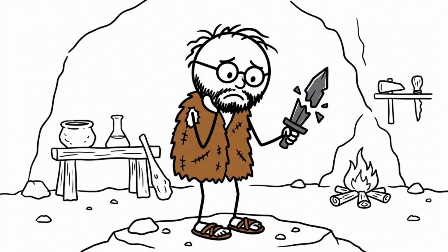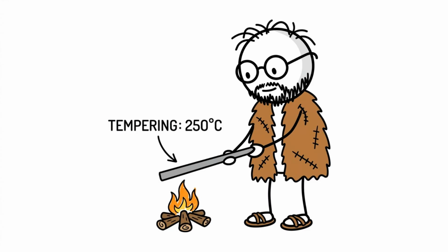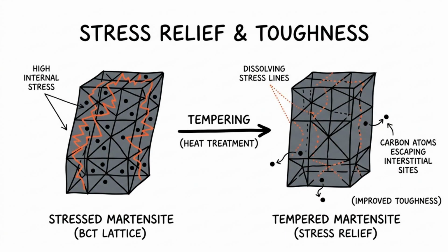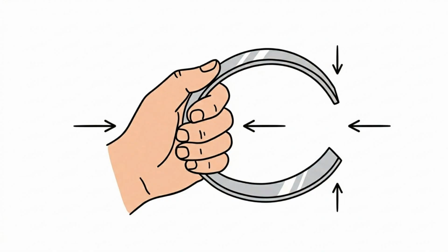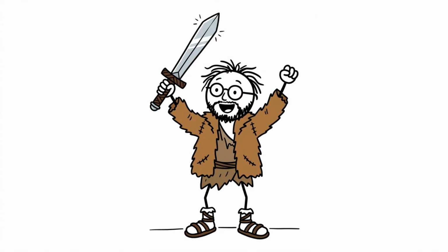You must temper the steel. You heat the quenched steel gently. You heat it to about 250 degrees. This heat releases some internal stress. It allows a tiny amount of carbon to escape. The metal becomes tough. It can now bend without breaking. It will hold a razor-sharp edge. You have successfully forged steel.